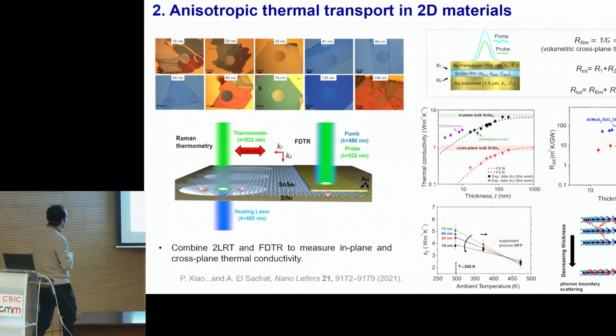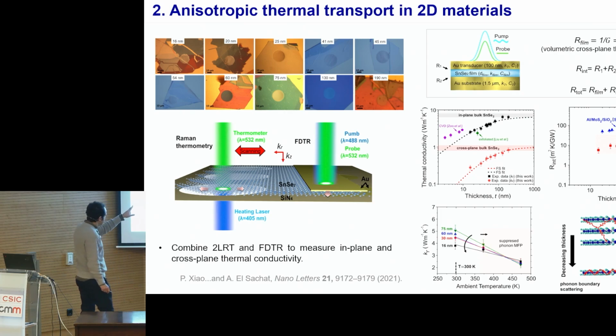Okay, let's go to the second part, which is how we can measure the anisotropic thermal transport in 2D materials. Here we used two complementary thermal characterization techniques, the two-laser thermometry and the frequency domain thermoreflectance. With the first technique, we measure the in-plane thermal conductivity of these flakes, and with the second technique, which is the right part of the image, we measure the cross-plane thermal conductivity.